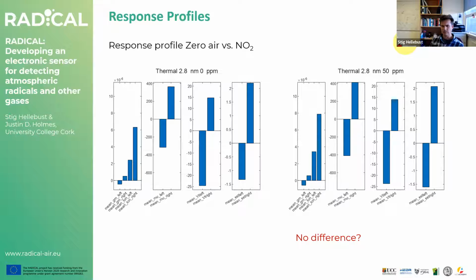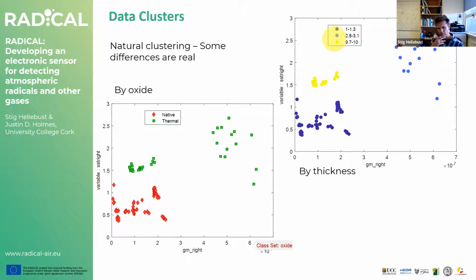Because a sensor, of course, is all about sensing something. But we can have a closer look at some of these measurements. Like I said, the shape of that curve. So, for example, if you look at the slope of that IV curve and the subthreshold slope, which is what I have here in these two variables, we have the slope and the sub-threshold slope. It turns out that this actually allows us to separate the native oxides from the thermal oxides.